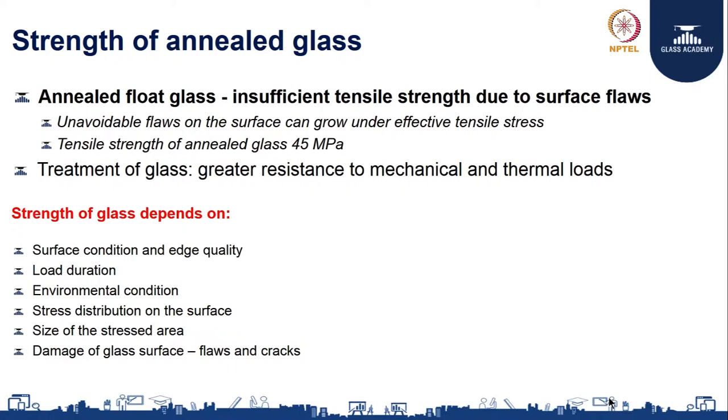The cut quality determines the edge quality, and the edge quality can be maintained by having proper grinding of glass. The grinding can range from simple arrising to chamfering the edges alone, or having a face grinding. The thicker the glass, it is better to have full face grinding.